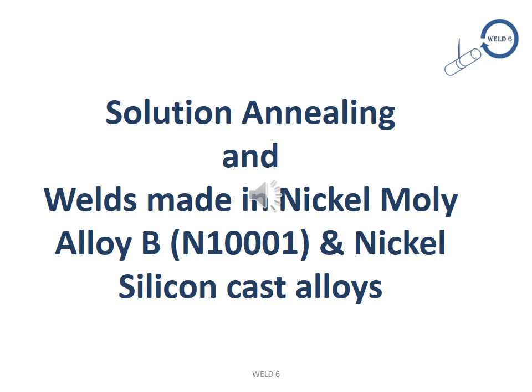Are all nickel and cobalt based alloys exempted from PWHT? The answer is no. Welds made in nickel molybdenum alloy B, UNS number N10001, and nickel silicon cast alloys are commonly solution annealed after welding to restore corrosion resistance to the heat affected zone. Rapid cooling from the solution annealing temperature is necessary to avoid formation of detrimental metallurgical phases, which can have an effect on mechanical properties and corrosion resistance.